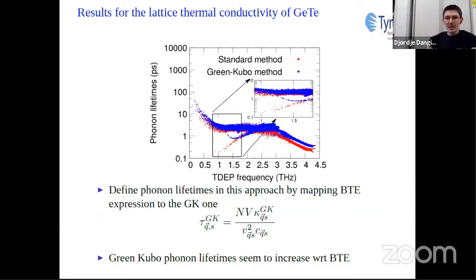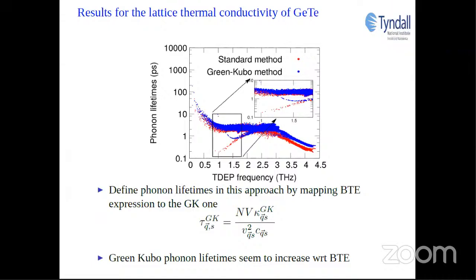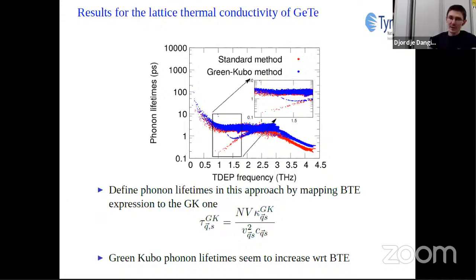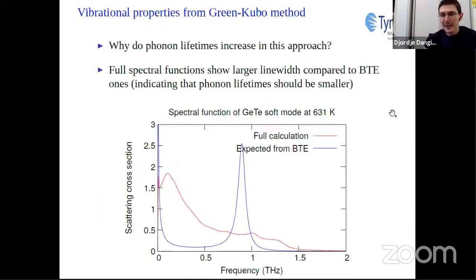Okay. Why is there an increase in lattice thermal conductivity going from the Boltzmann transport equation to the Green-Kubo approach? One can look at it by mapping the Green-Kubo expression to the Boltzmann transport equation expression to extract phonon lifetimes. If we do that, we calculate the phonon lifetimes in the Boltzmann transport equation and the phonon lifetimes in the Green-Kubo method as defined here, and we find that the phonon lifetimes in the Green-Kubo method increased substantially, especially for the region of the soft modes. Well, does that make sense?